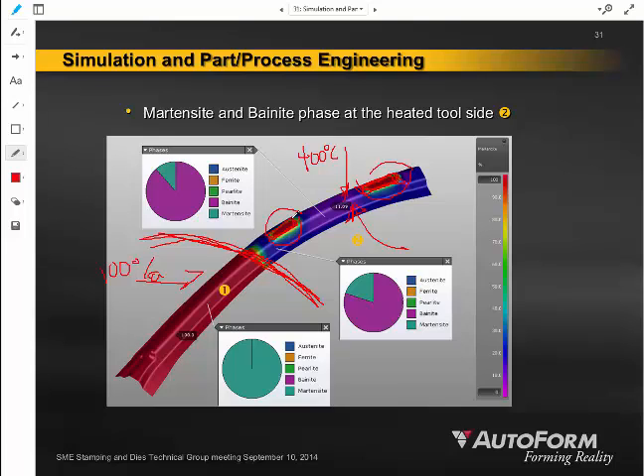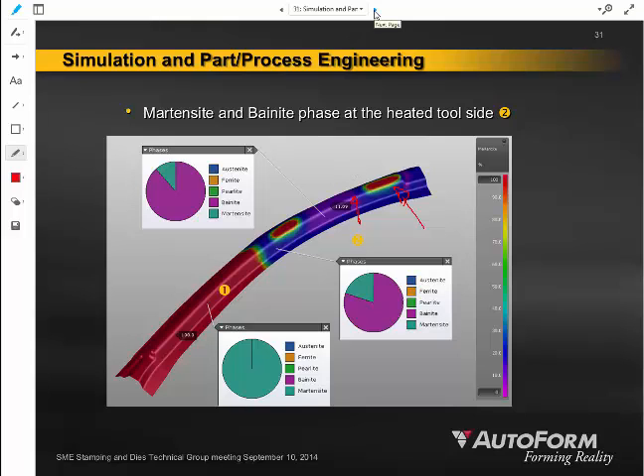And what happened is that we ended up with areas having more martensite than perhaps people might have planned for. And what that means is that these two areas are going to be stronger than the areas adjacent to them. And that could lead to maybe assembly problems, or that could lead to a difference in product performance that they didn't perhaps foresee or plan for.